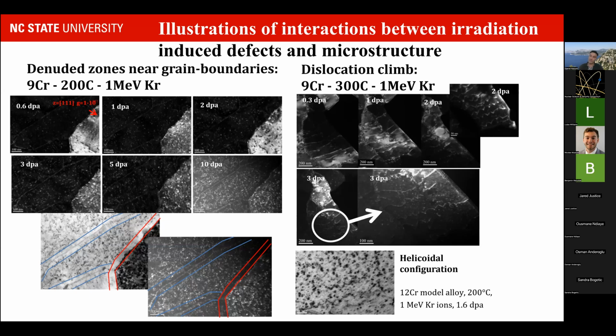What we have to realize is that transmission electron microscopy pictures are 2D projections of a 3D configuration. So in the material itself, the zigzag aspect will translate most likely to a helicoidal configuration. And there have been some simulation studies that show that to climb, a dislocation can modify its shape into a helix, and it will make it easier for it to climb. That process of climb can be at the source of the enhancement of creep under irradiation.